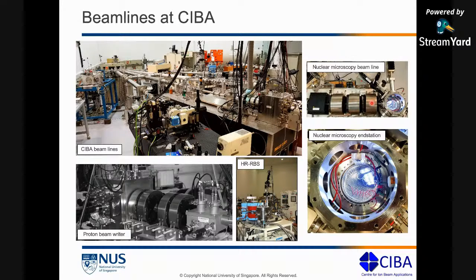So this one also is a focusing beamline, but this is more of a general or universal beamline in CIBA. What that means is we don't only use this for focused beam experiments. I use it for RBS, I use it for ion channeling measurements, I use it for ERDA, depending on what kind of detection system we have in there. So this is more like a generic beamline, whereas the other is more like a dedicated beamline. The focusing ability in that one is much better than here. There they have even achieved a focused beam spot as small as, I believe, 19 nanometers by 40 or 45 nanometers.